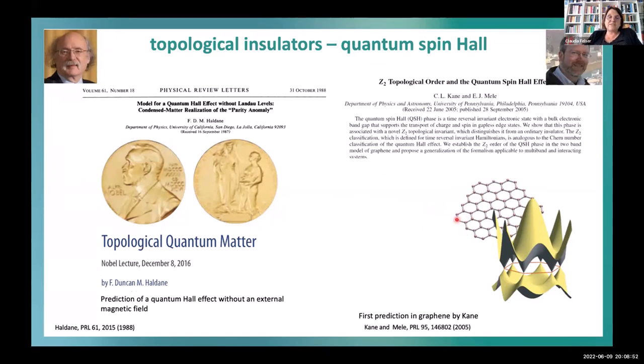So when I would have seen the paper at this time, I probably would have overlooked it, I would maybe have said it's something special for some specialists, but already at this time, people recognized this is really material oriented and opens a new pathway to find more topological materials. And the only thing here was that they thought, instead of the intrinsic magnetic moments which we have in a magnetic material, maybe spin orbit coupling is enough. And they recommended graphene, but graphene is a light element. And also we deal a lot with spin orbit coupling if you look for skyrmions and so on. So in magnetic material science, we all know that graphene is a light element. So spin orbit coupling is here not the ideal value if you want to achieve bigger effects.